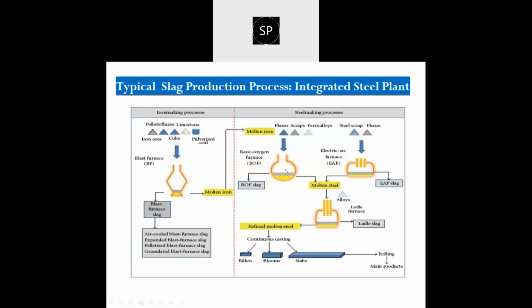In the basic oxygen process, the majority of raw material should be the hot metal, meaning the freshly prepared pig iron through the blast furnace process. While in the electric arc furnace, you can go for steel scrap, and 40 to 50% steel scrap can be utilized along with the hot metal for the production of steel. In this type of furnace, once again, the slag is generated in the form of impurities at the top of the furnace, and then it is tapped, and when it is air cooled, it becomes the electric arc furnace steel slag.